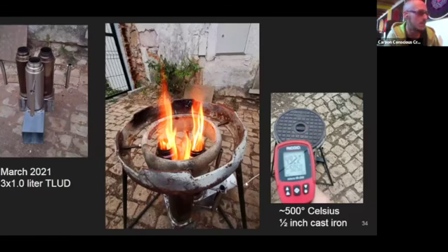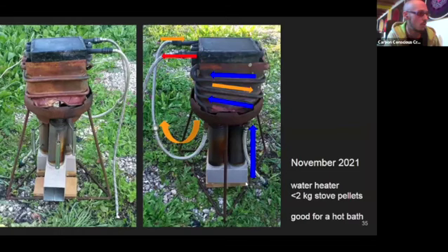And then to test things even further, I made a small hot water heat exchanger to be able to take hot baths heated directly with the gasifier. And it takes less than 2 kilos of wood, and that's enough to get a hot bath of water. So that shows how efficient the system works. And actually, on top of the heat exchanger, I can put my hand when it's running, because the heat exchanger is so efficient at pulling all the heat from the gasifiers.